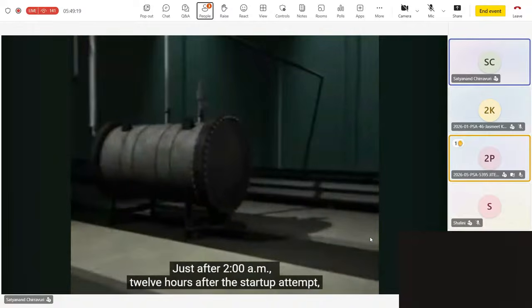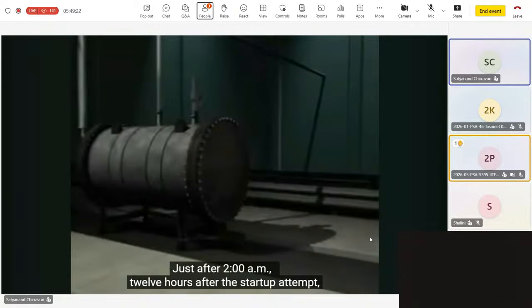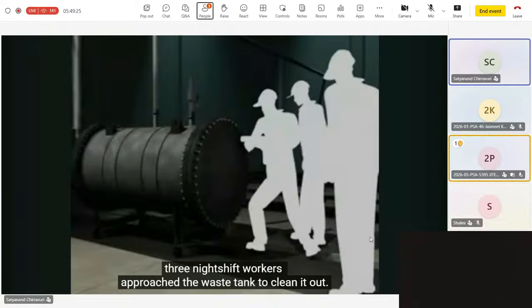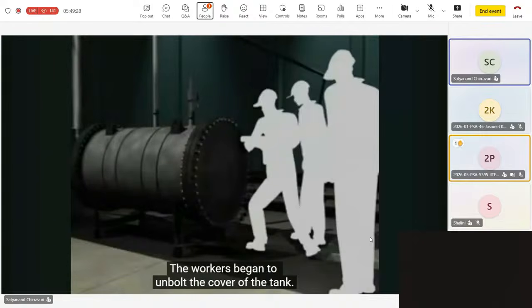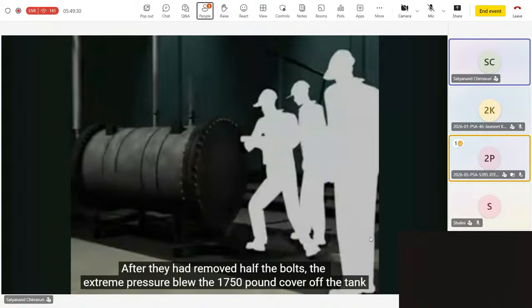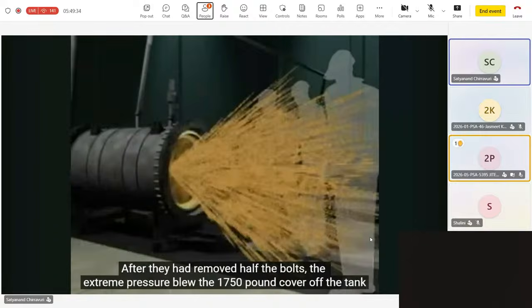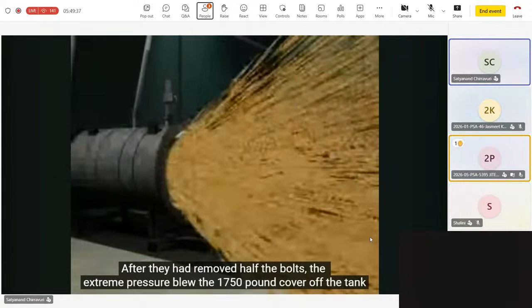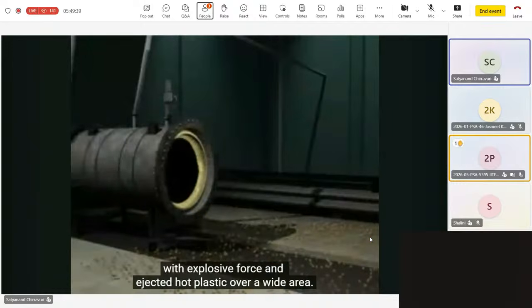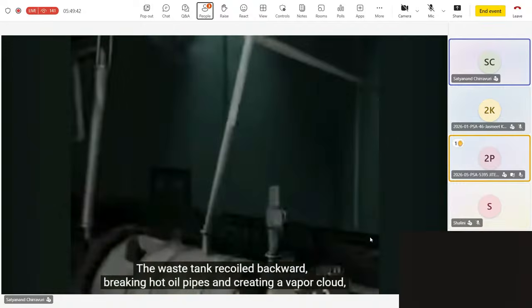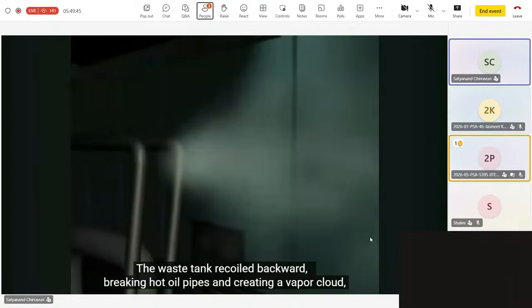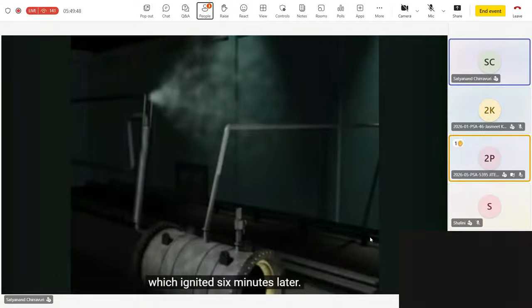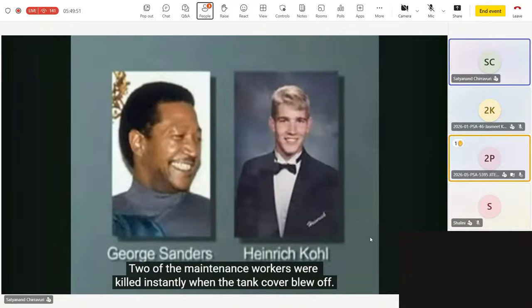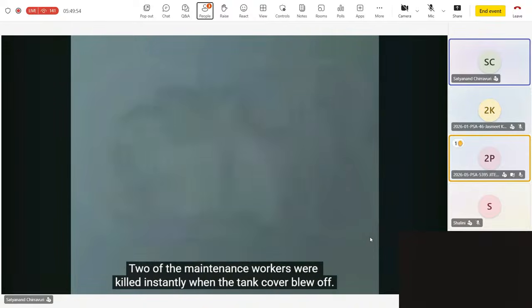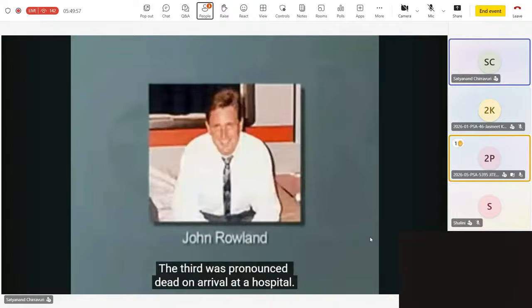Just after 2 a.m., 12 hours after the startup attempt, 3 night shift workers approached the waste tank to clean it out. The workers began to unbolt the cover of the tank. After they had removed half the bolts, the extreme pressure blew the 1,750-pound cover off the tank with explosive force and ejected hot plastic over a wide area. The waste tank recoiled backward, breaking hot oil pipes and creating a vapor cloud, which ignited 6 minutes later. 2 of the maintenance workers were killed instantly when the tank cover blew off. The third was pronounced dead on arrival at a hospital.